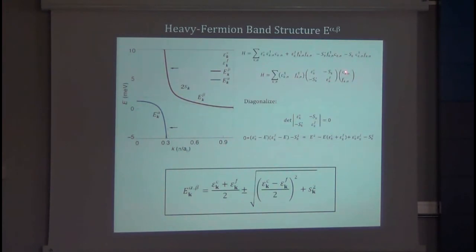Now you're describing a new eigenstate, which is going to be a linear combination of c and f electrons. When you diagonalize, you'll find two new bands. We call them capital E of k, A and B. Here's one, and here's the other. And these two bands are made up of hybridization between the light c band and the heavy f band, which are embedded in the equation, plus the only other thing in here is the hybridization matrix element. In theory, of course, this picture has been available since the early 1970s, like 1974.